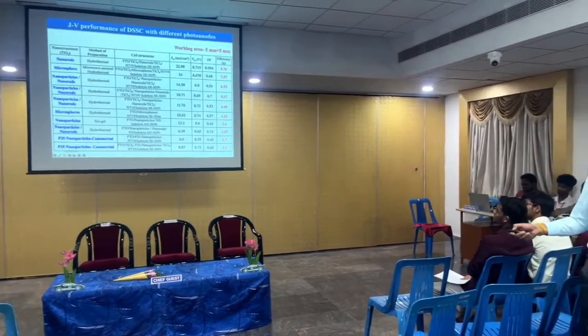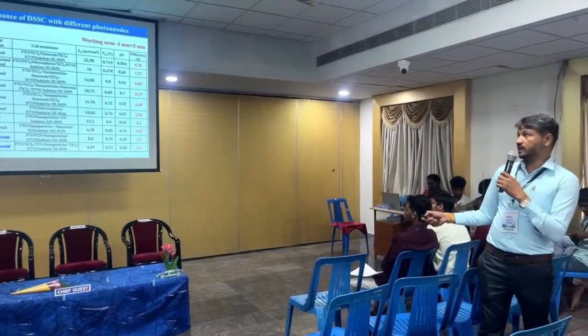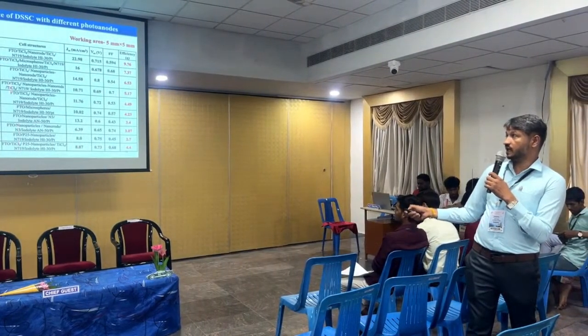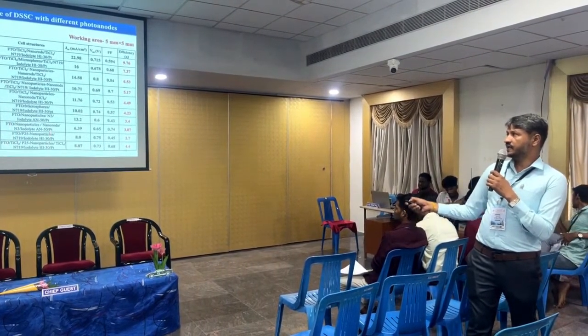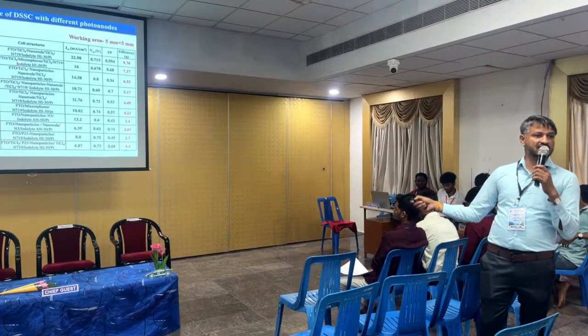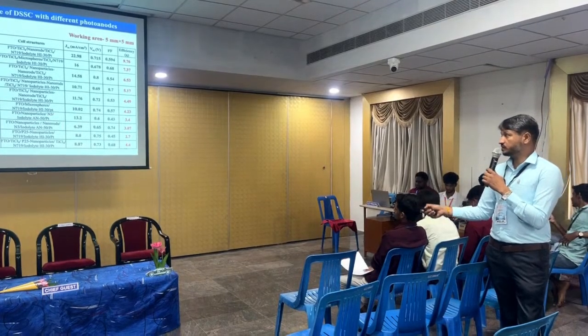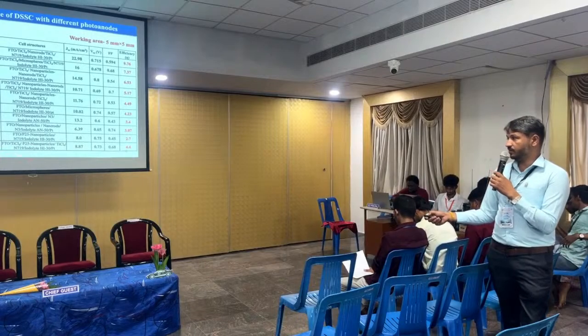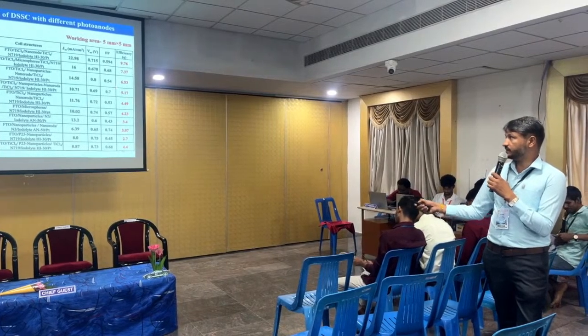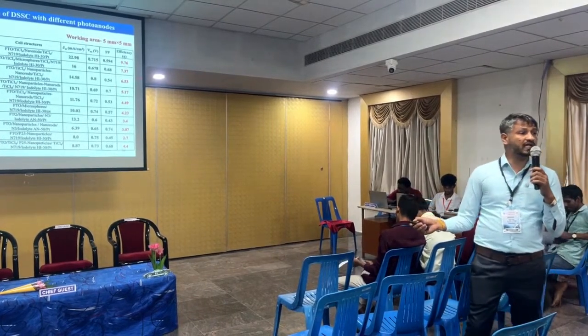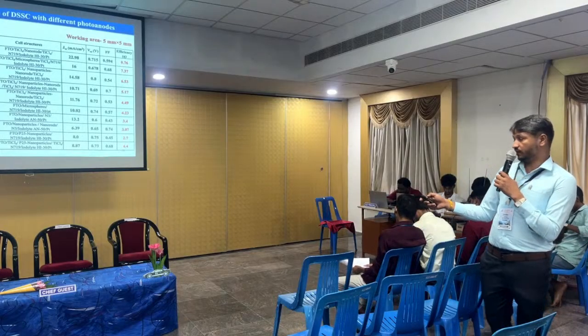This is a very beautiful structure I got, and that's why I am keeping it. So I prepared so many nanostructures with different methodologies, hydrothermal, sol-gel, and different combinations of solar structures we used. So you see the progress. We started with the commercial one at 4.4% efficiency. We reached close to 10% efficiency over a period of time.